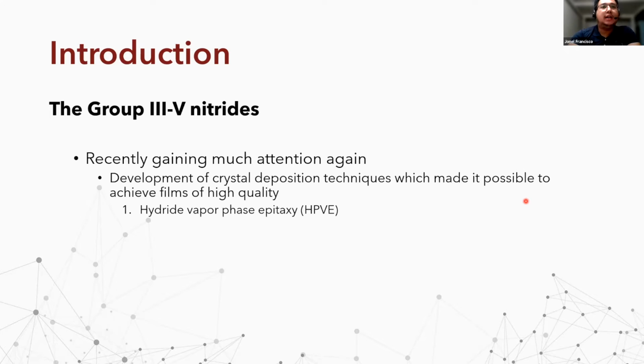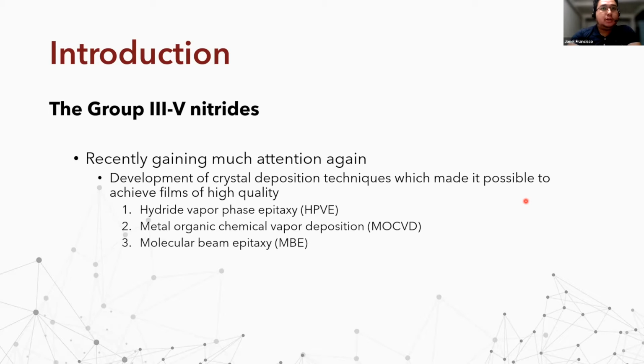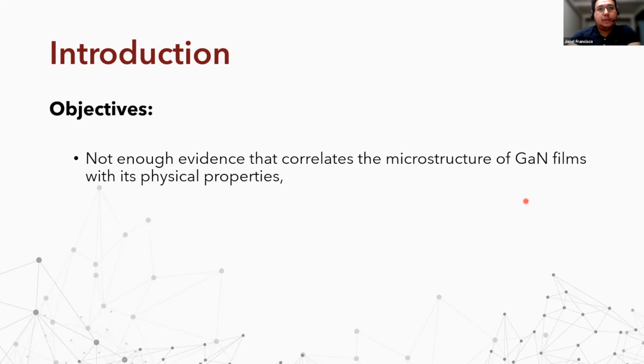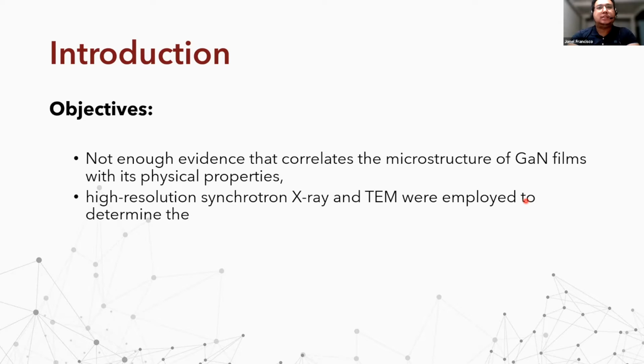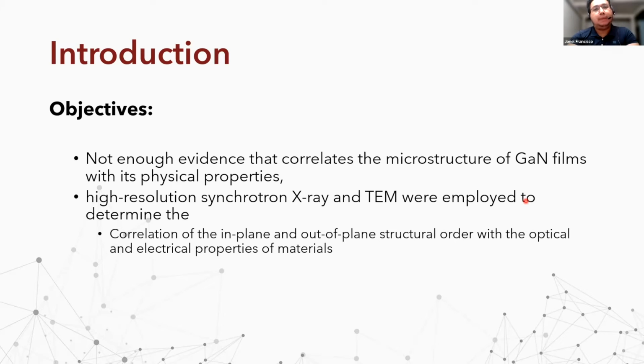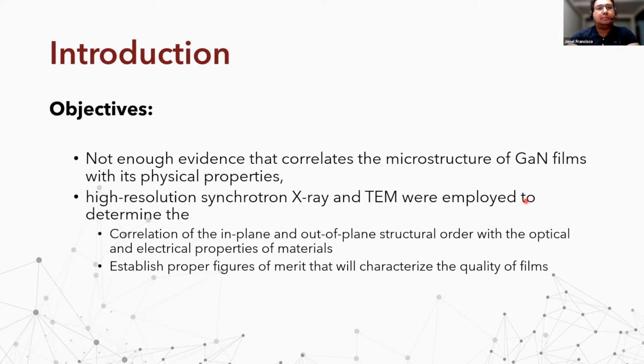Among these methods are hydride vapor phase epitaxy, metal organic chemical vapor deposition, and molecular beam epitaxy, the latter being the one employed in the current study. Another problem arises, since there is not enough evidence that correlates the microstructure of gallium nitride films with its physical properties. High-resolution synchrotron X-ray and TEM, transmission electron microscopy, were employed to determine the correlation of the in-plane and out-of-plane structural order with the optical and electrical properties of materials, which could help in establishing proper figures of merit that will characterize the quality of the films.